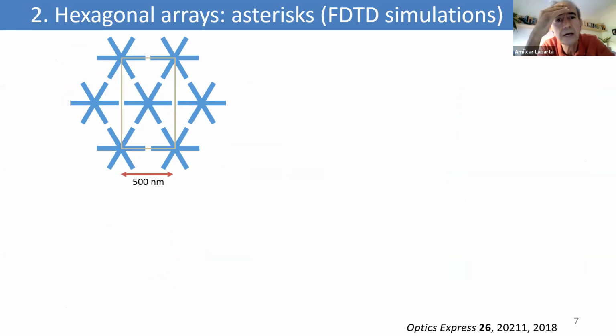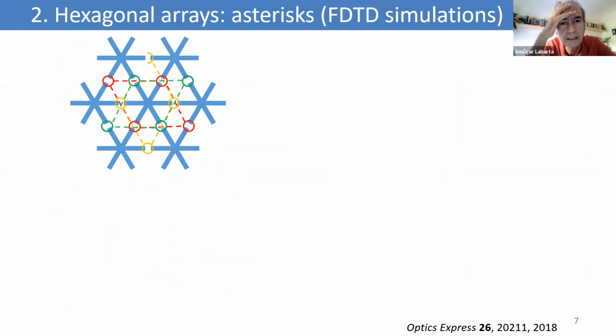Here we have asterisks in a triangular lattice, and the origin of geometric frustration in this case is just the competition between the three triangular sublattices that the gaps form. You have these three triangular sublattices of gaps. They are rotated 60 degrees with respect to each other, so there is a certain competition between these